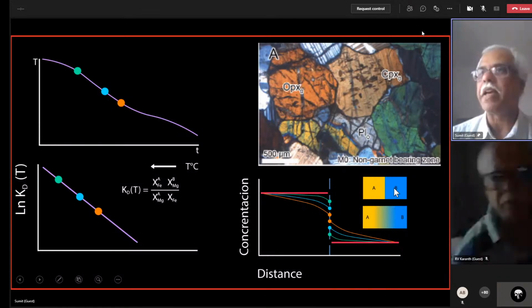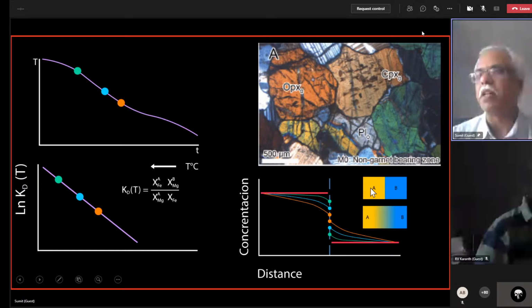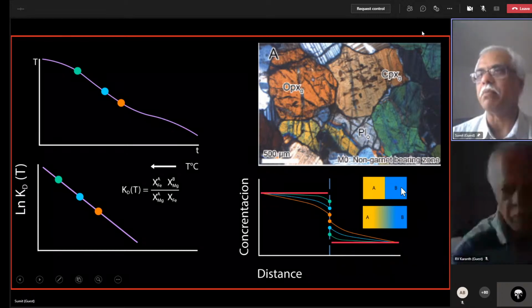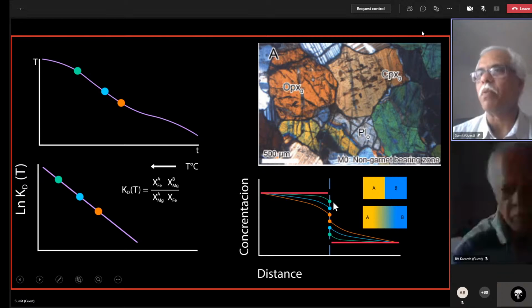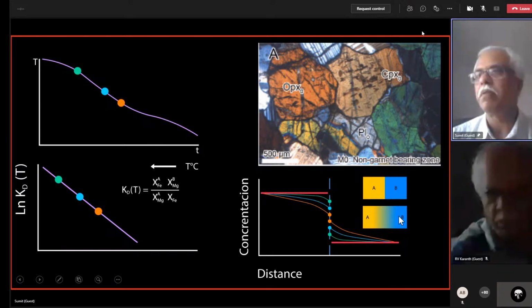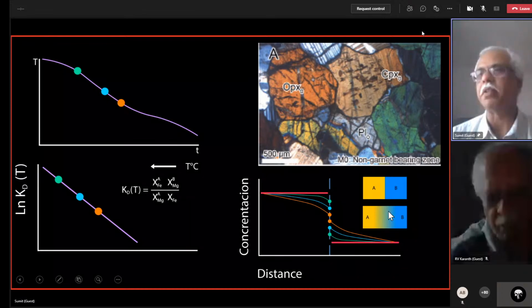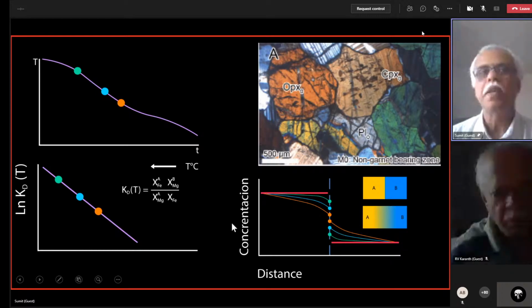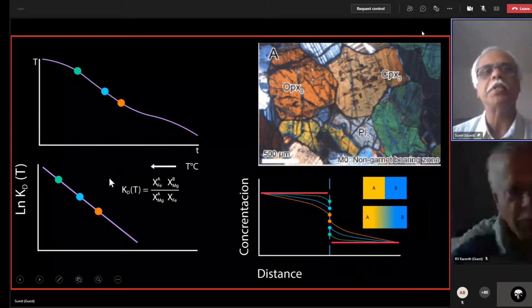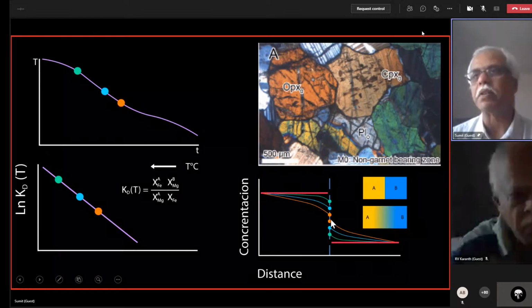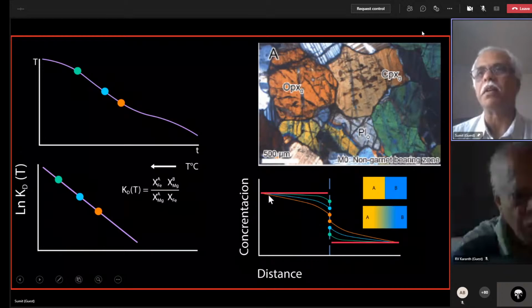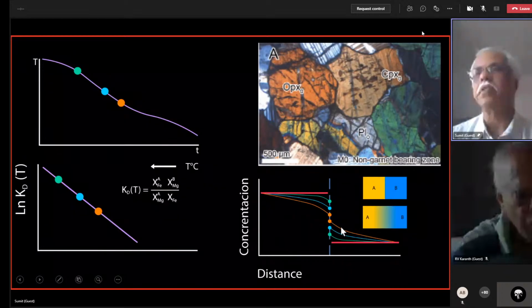And that's shown schematically here in this diagram. When you have two minerals, A and B, initially they have a yellow concentration for A and a blue concentration for the B. Once you start cooling and start forming some zoned crystal, you form here diffuse boundaries. The green and the blue and the yellow begin to get mixed with each other. And so this continues on. You cool further, you come to the orange grain, and this is your orange KD that would correspond to that temperature. And then the boundary once again goes to the value it should, and the crystal is now even more strongly zoned, and the thing continues on.